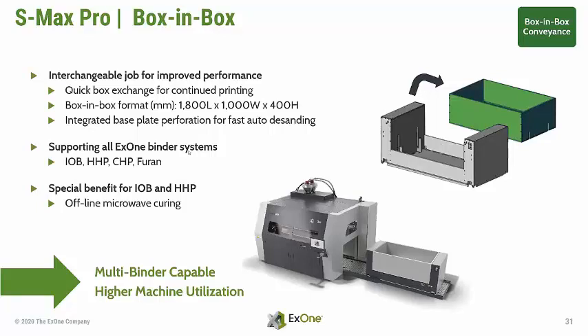Due to the auto-desanding capability, the reduced job height of 400 millimeters is not becoming a performance issue. As with auto-desanding, a one-layer part print job will improve productivity by shortening the line index times. With this capability, the Box-in-Box system can support all binder systems, but it will provide certainly the most benefit for the inorganic and hot hardening phenol process.